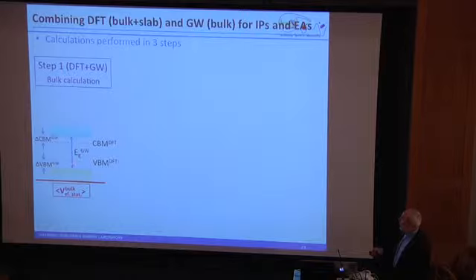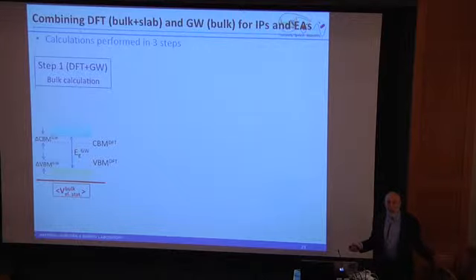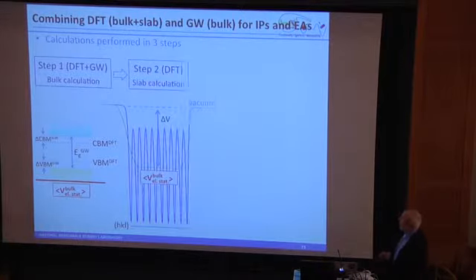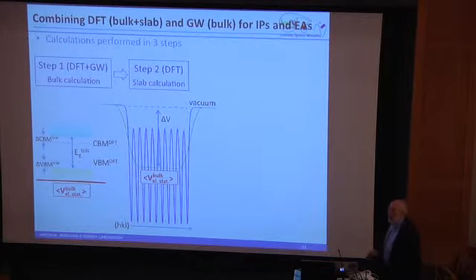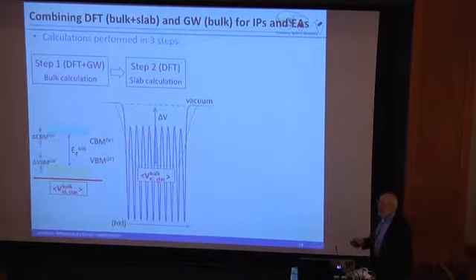So this gives us a calculation of the bulk value, but not given versus any reference, right? So then we do a calculation where we use DFT and we break it into slabs and we do an electrostatic calculation, and we can then connect the slab to the vacuum level. If you can do that,